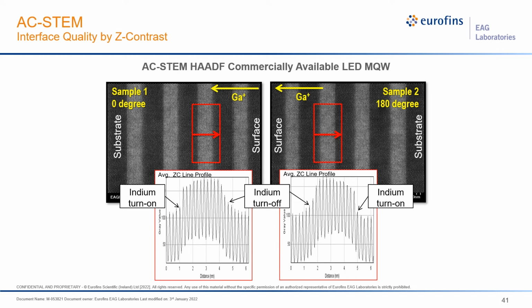And if we take an average line profile through this red box here, you can quantitatively measure this kind of change now with atomic precision. So on the substrate side, you can see as the indium turns on, you get this really nice abrupt step up, and as you grow this layer and then turn the indium off, you get a much more gradual change in composition. So either the indium is purposely being turned off slowly, or there's a residence time for indium in the system.